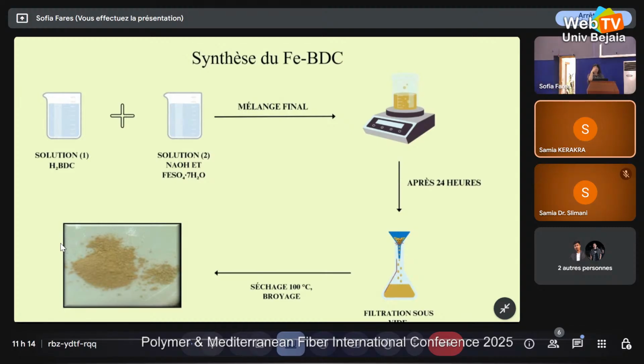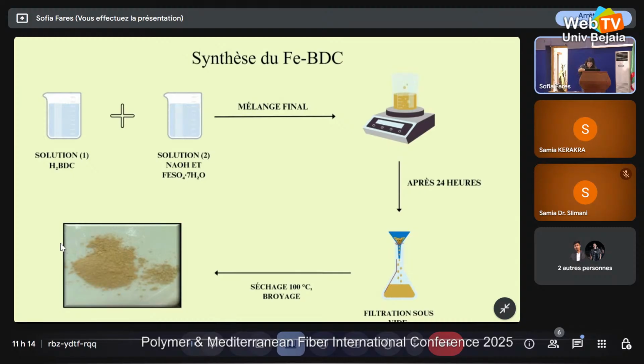And the second solution: here our iron salt was dissolved in distilled water and stirred for 15 minutes. For the final mixture and recovery, the two solutions were combined and stirred overnight. After 24 hours, the resulting precipitate was filtered under vacuum, washed with DMF, and dried at 100 degrees Celsius overnight, then ground into a fine powder. This is about the synthesis of the MOF.